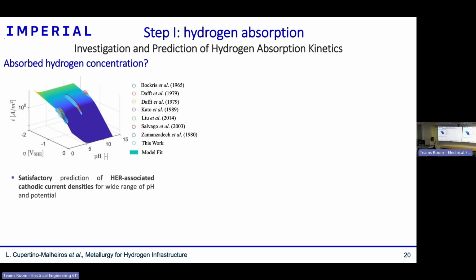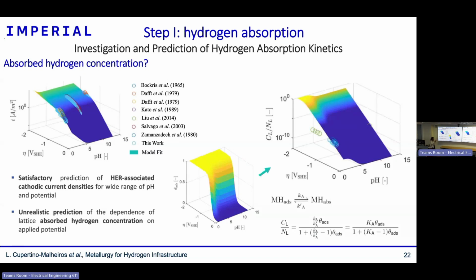But when it comes to really predicting how much hydrogen gets absorbed, what we see with this model, here on the y-axis, is the absorbed hydrogen at the surface. One indicates that the surface is fully saturated with hydrogen. And what we see with this approach is that the model tends to give a completely saturated surface quite quickly. That completely overestimates how much hydrogen actually gets inside the metal and the dependence on overpotential. So this is something that I'm still working on.